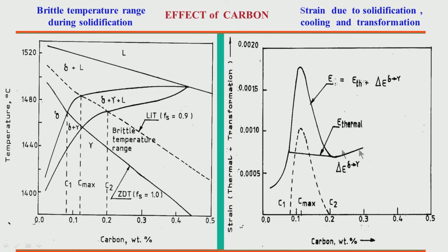So, you can make out from these figures how different carbon contents will behave, whether the characteristic of the grade will be depression or sticking. This intrinsic behavior, either sticking or depression, depends on the chemistry. So, accordingly the casting parameters have to be selected to take care of these issues, so that the quality of the cast product is relatively good.